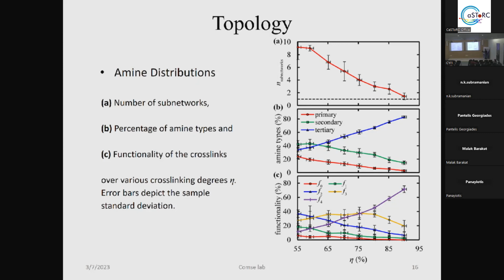The same physical meaning, in other words, is here. The tertiary amines are increasing because the bonds are linked with the other parts of the system, while the primary and secondary amines decrease. And we also see the same here, that the functionality 4 of the system increases because we have a totally whole glass system, in contrast with functionality 0 to 3. Functionality 0, I mean totally melt.